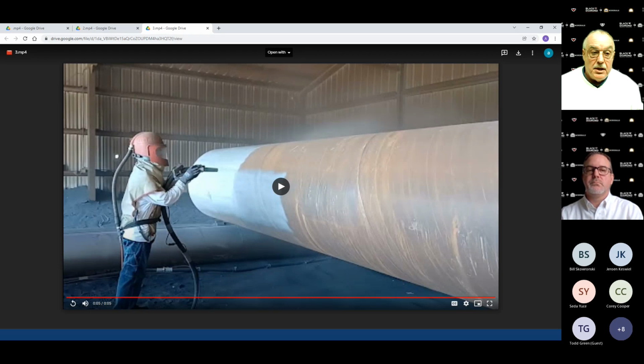What you don't want to do is turn it down so lean that you slow your production rate down. And there is a sweet spot where you have minimum consumption rate and maximum production rate, and that's what you want to adjust the micro valve to. And it's different for each abrasive.